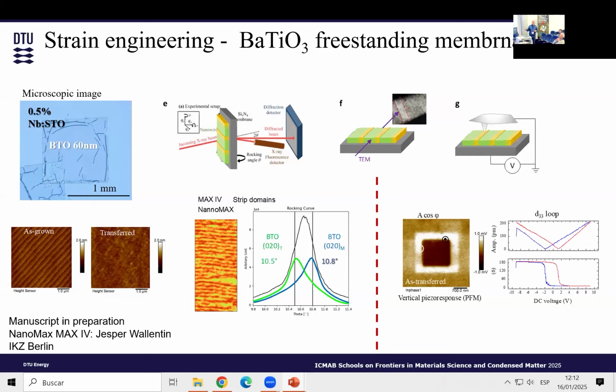Then we took it to the TEM, and we looked at it. We can still see a modulation in the strain of the material. So we can see differences. We tried to do PFM on the material. Globally, we can see that it's ferroelectric, but locally we could not identify ferroelectricity on this line.